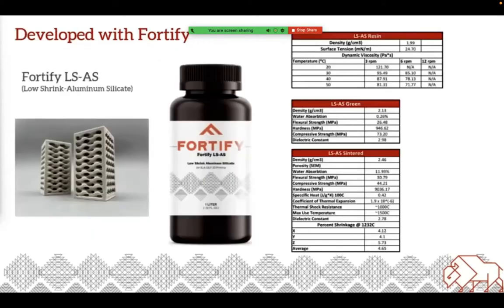So what materials have we developed for the Flux today? So far, we've launched 2 materials for the Flux machines. The first is LSAS, which stands for low shrink aluminum silicate. This material is a mid-grade alumina ceramic material that sinters at 1250 C. This material can be fired in a low-cost pottery kiln at cone 7. This LSAS material shrinks less than 5% and is isotropic in nature. This is really unheard of in the ceramic additive industry and is the only material of its kind.